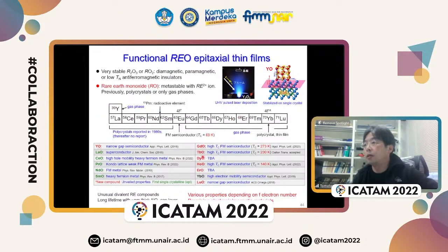So this red one is a new solid phase, and these are superconductors or semiconductors or ferromagnetic semiconductors, or ferromagnetic metals. So it is very interesting. In this case, by changing the 4F electron number, the physical properties are not so changed. But in the case of the rare earth monoxide, by changing the 4F electron number, the physical properties change very, very significantly. Some of them are superconducting, some of them are ferromagnets. So these are promising electronic and magnetic materials.